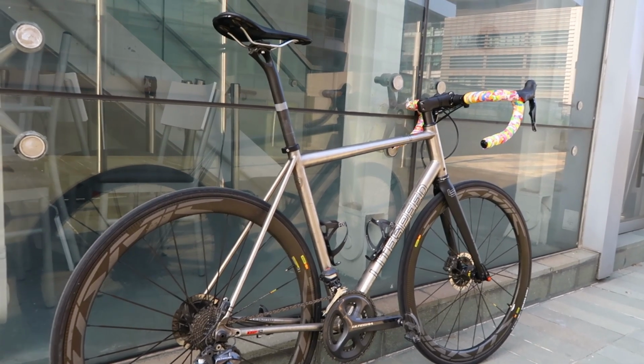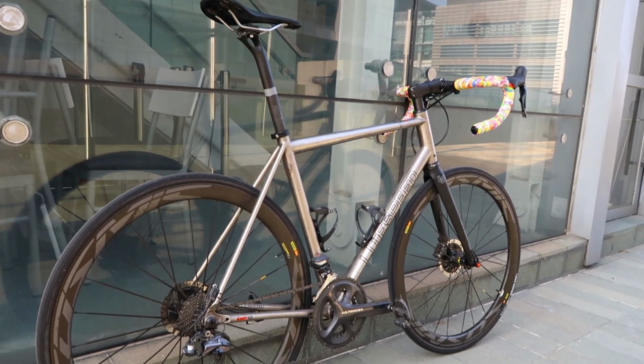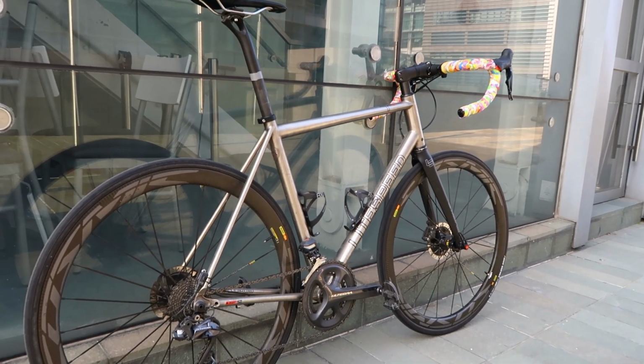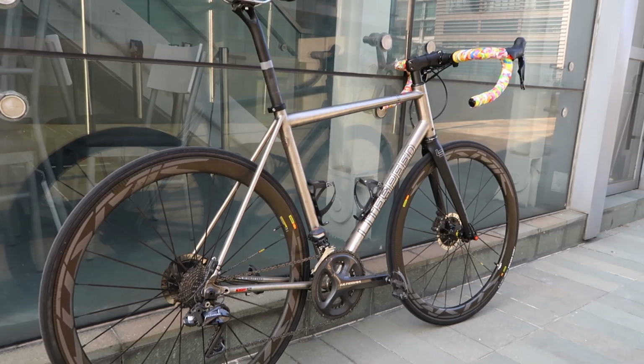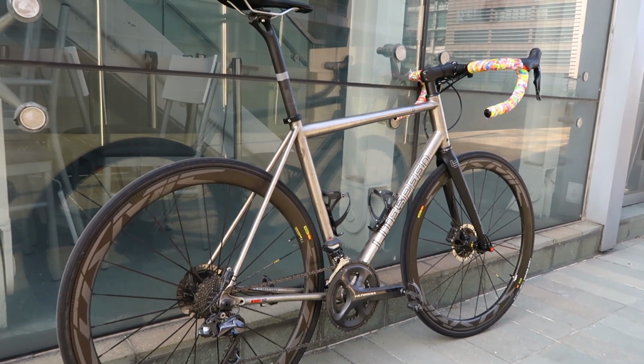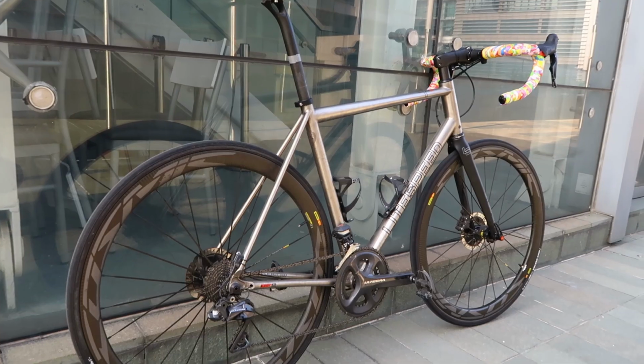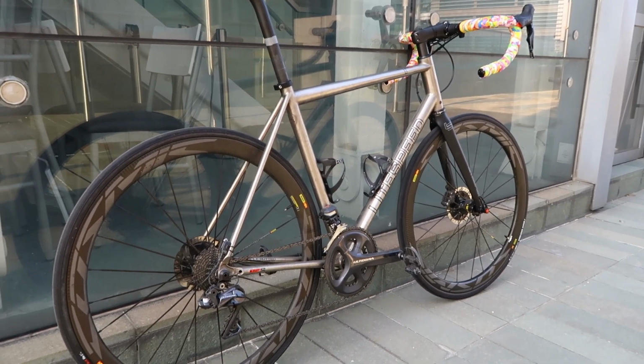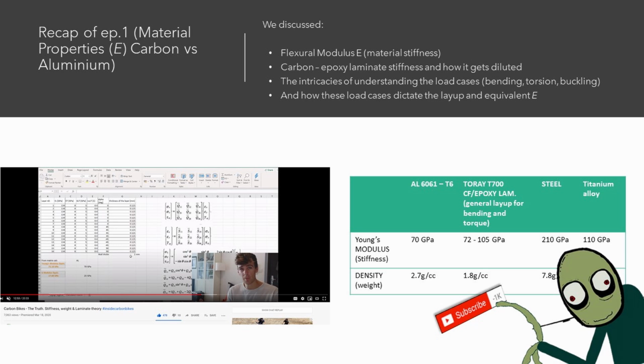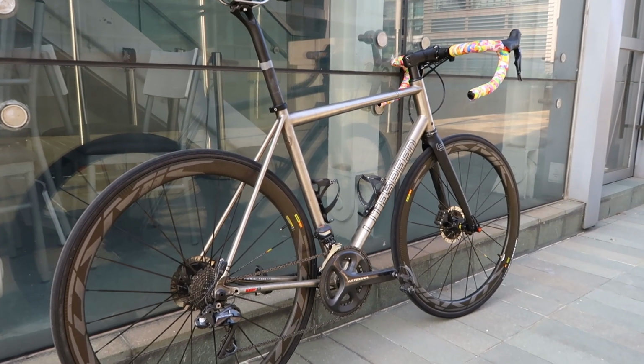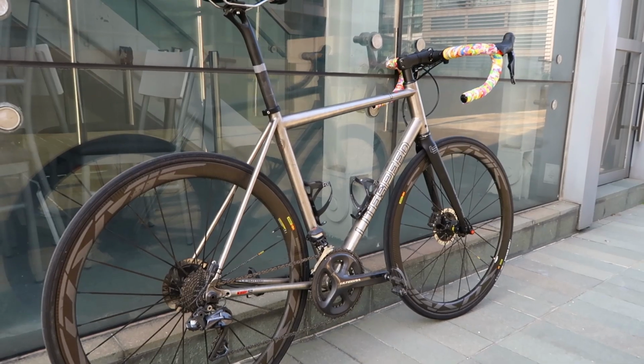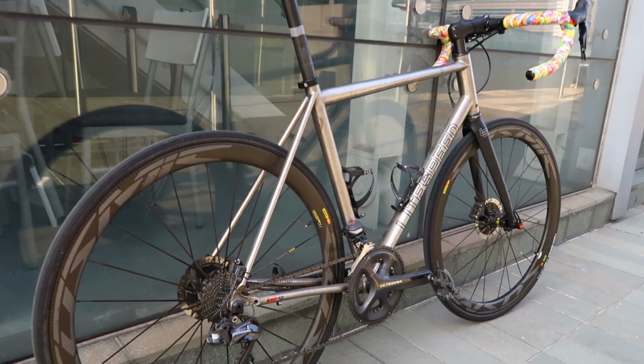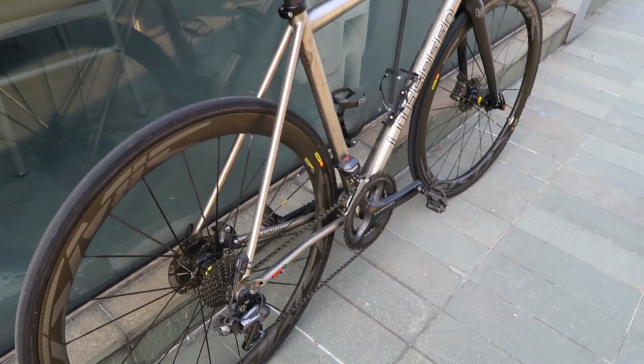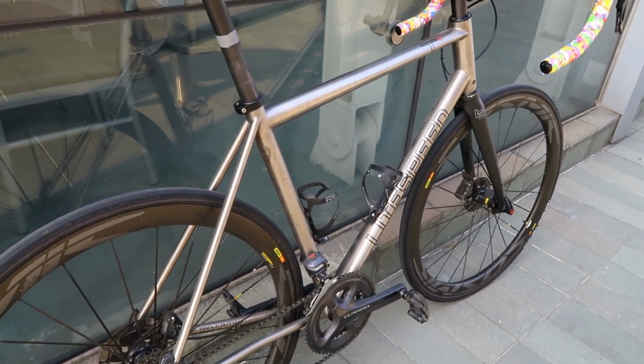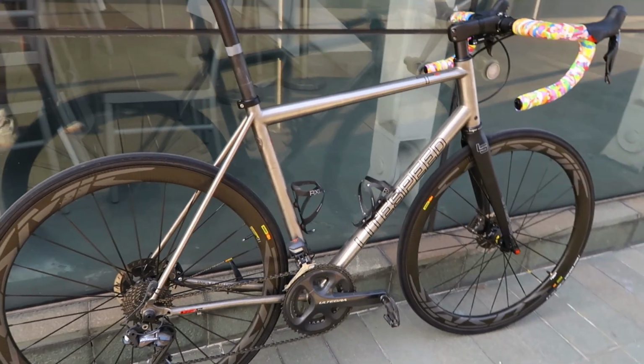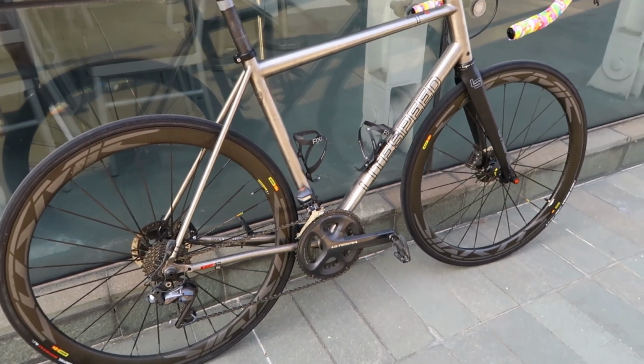And it happens that when you build a bike with the right tube thicknesses for the strength of the welds and everything, you do actually end up with a frame very similar to the mass of an aluminium frame and the same stiffness. Now, if we look at carbon as an example, in that video I did on Young's modulus, we looked at carbon fibre and the flexural modulus you get out of carbon fibre when you lay it up into a bike frame, and it's never what is quoted by Toray as the tensile modulus, because you can't just make a bike frame out of 0-degree fibres. And actually we found that when you make a complex layup for a bike frame that can take torsional, bending and buckling loads, the flexural modulus that you end up with is somewhere in 70 to 80 gigapascals, so not far off aluminium.